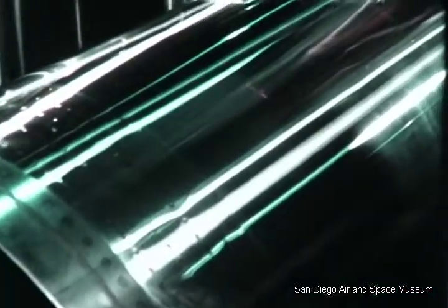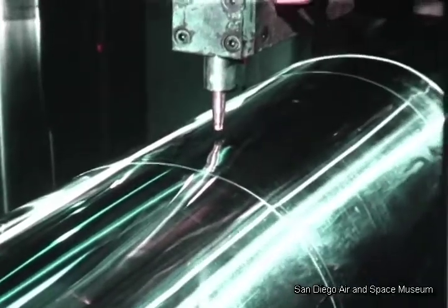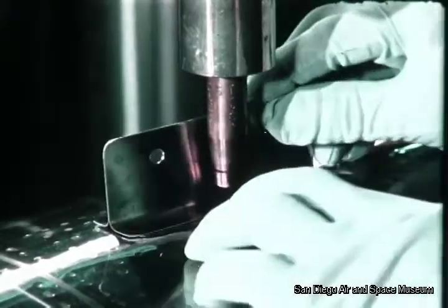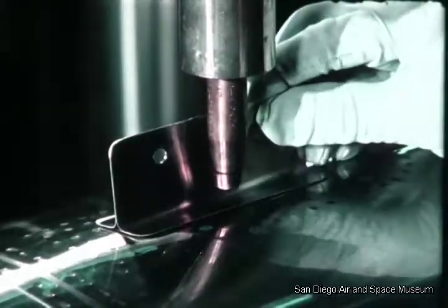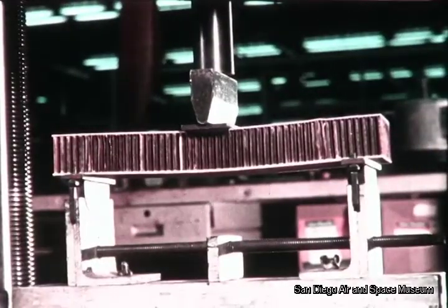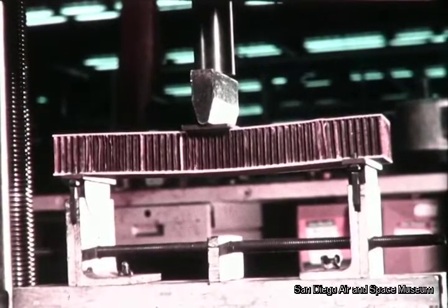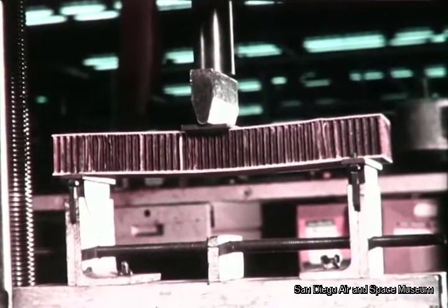The fatigue life of the nickel-alloyed weld is excellent. We fabricated test tanks with and without nickel foil under test brackets and tank seams. With foil, fatigue life was greatly improved. Confirmed the soundness of the fairing's design. Each sample surpassed design requirements before it failed.